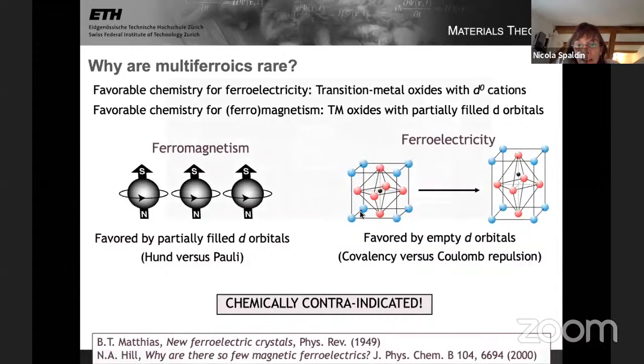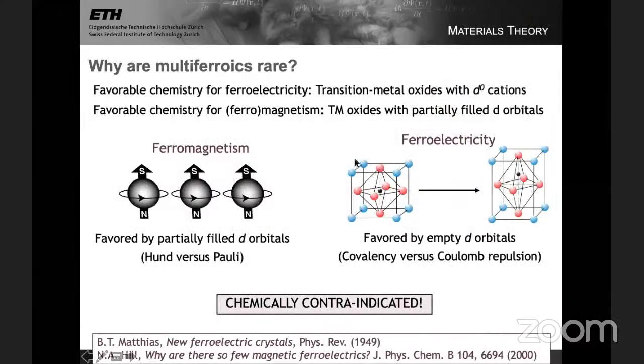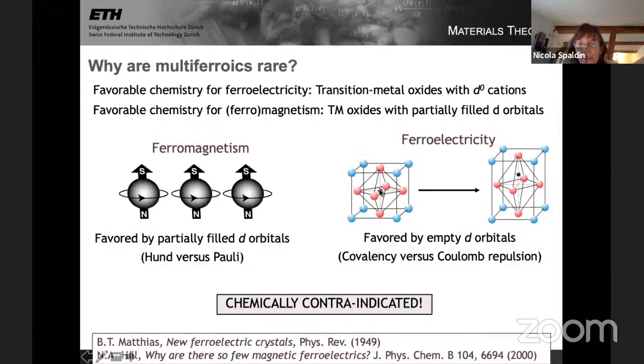If I look again at barium titanate, here's the D0 titanium in the center, and barium 2+ in the corner. If I replace this barium 2+ by an F electron system, a rare earth, and we'll look at the case of europium because this is a good divalent rare earth, then of course I can keep the ferroelectricity of the D0 transition metal cation and combine it with F electron magnetism from the europium. So absolutely, that's going to be one of the strategies that we've used.